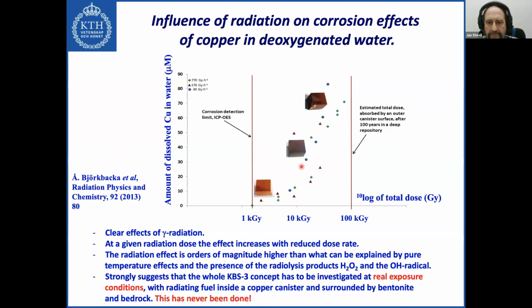So the important thing here is that even if you would go down to natural gamma radiation that you have in the real repository conditions, what these results tell us is that these results may still be quite relevant, because they show that when you go down to the lower dose rates, there still might be quite pronounced corrosion effects. But of course, when we go down to the real conditions, we have no results for that. We have never seen the whole KBS3 concept tested with gamma radiation inside. So as long as we cannot do that, we cannot really tell, considering all these observations we have here, what will really happen under the real repository conditions.